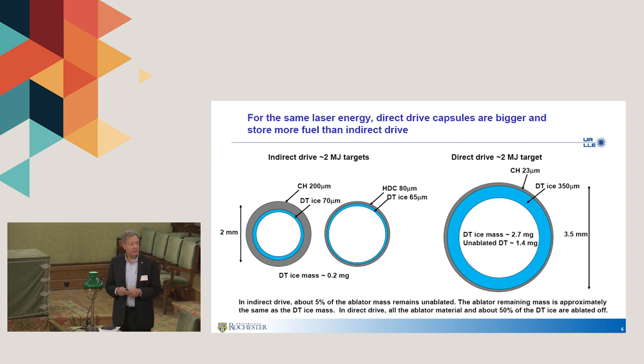There is another benefit of direct drive capsules, which is that the ablator, which is a shell of plastic, the outer shell that you see, is very thin. Instead, for indirect drive, since you're using X-rays, it is very thick. The X-rays do not ablate the ablator completely, because you need some ablator left in order to protect the deuterium and tritium, which is the thermonuclear fuel, from the X-rays. Instead, direct drive doesn't need that protection, so you can ablate all the ablator, and what you are left with is just the thermonuclear fuel. So that's also an advantage.